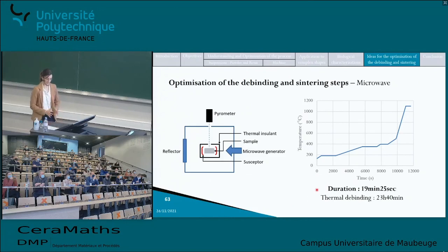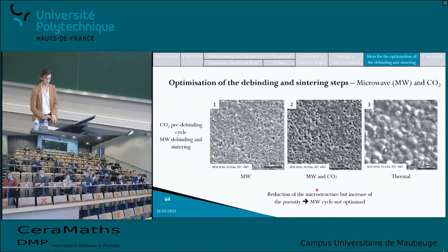So again, three different samples were printed: one that only went through the microwave debinding and sintering, one that went through the microwave debinding and sintering but also a pre-debinding cycle with supercritical CO2, and one that went through the thermal debinding and sintering steps. The first thing that appears here is that the microwave cycle was not very optimized because there is still a lot of residual porosity inside the sample. However, even though they had defects, it was possible to obtain samples and to handle them.